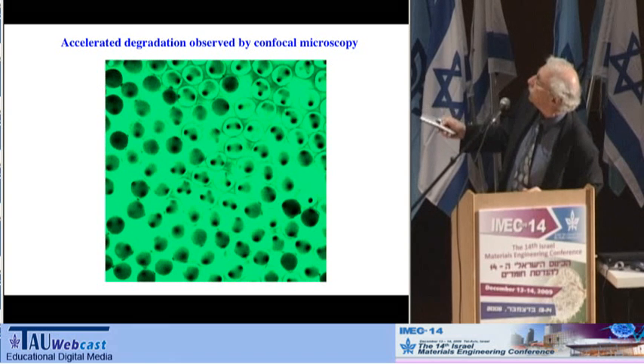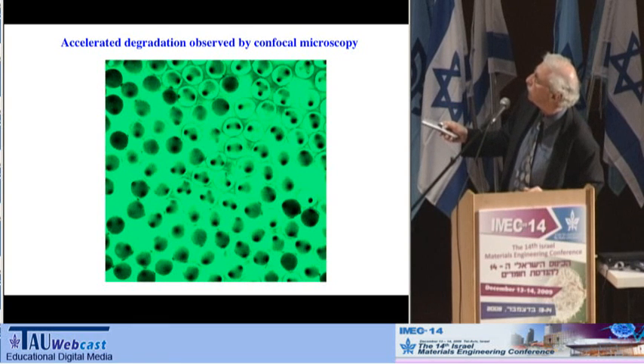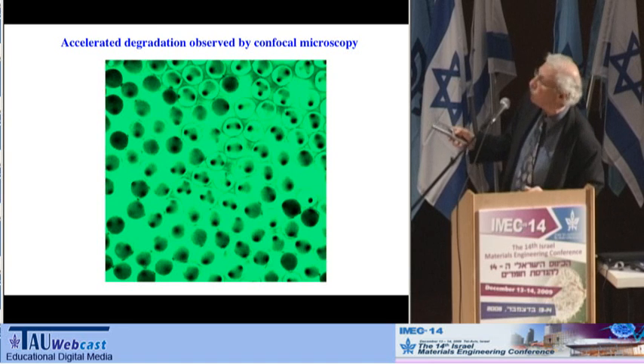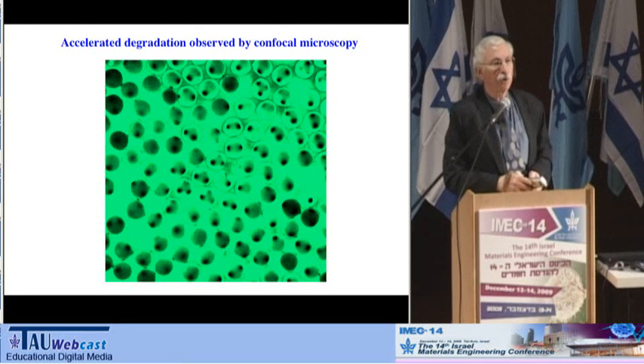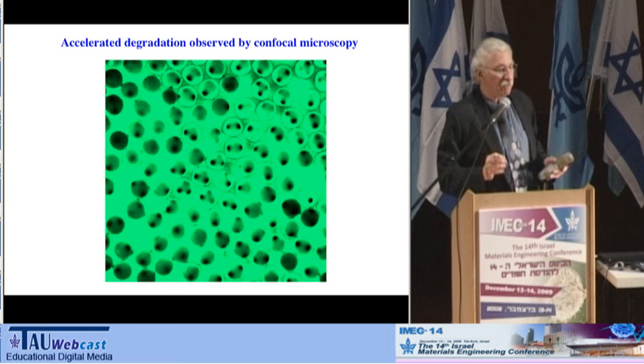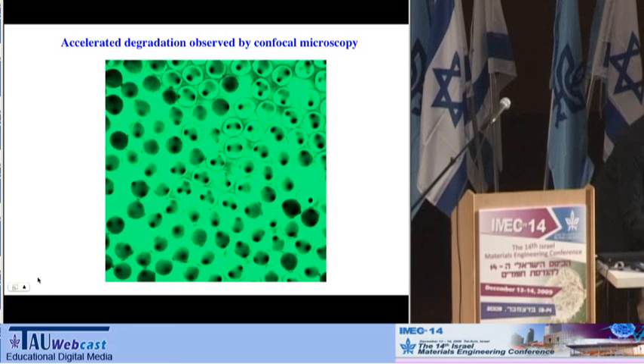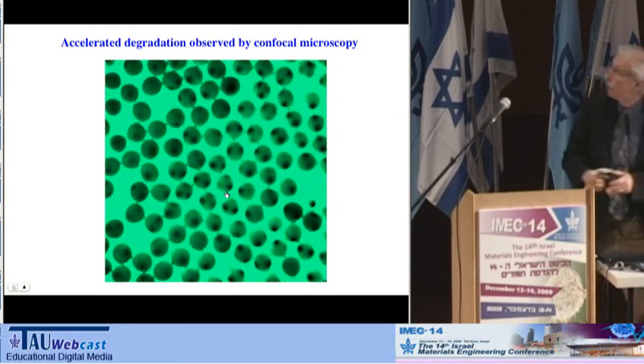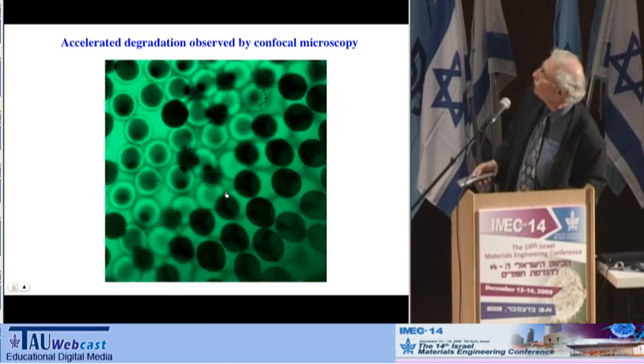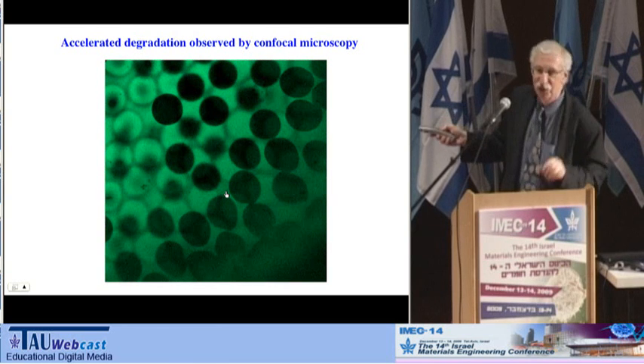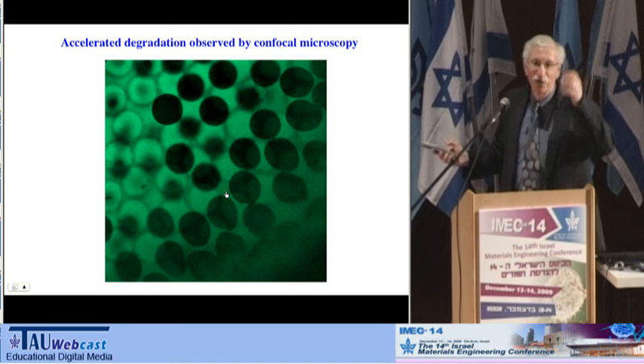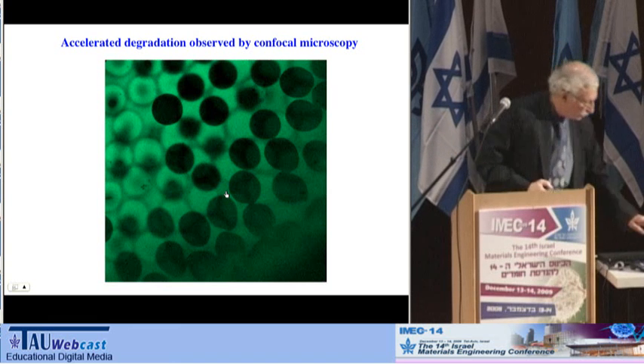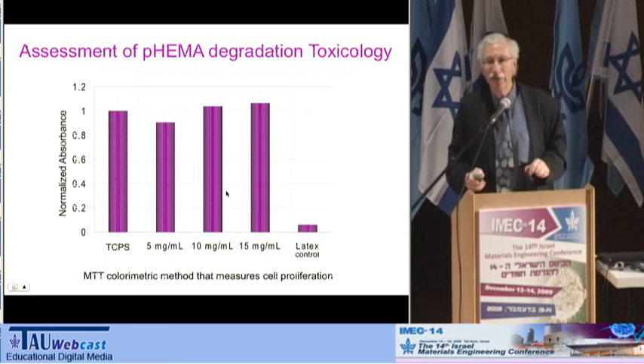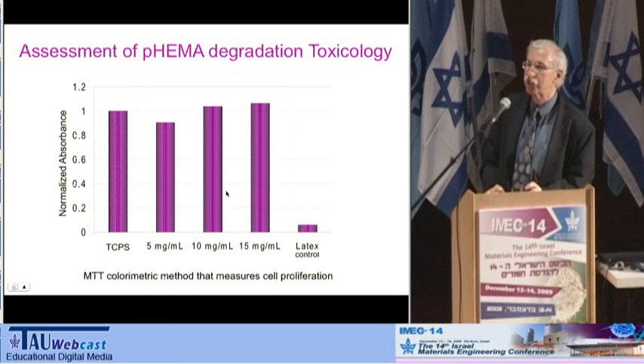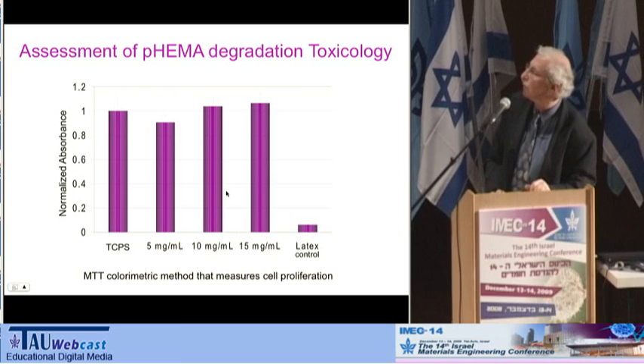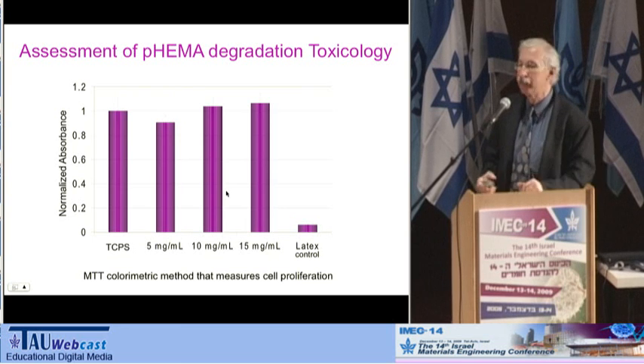And this is a section of this material on the stage of a confocal microscope. We're just going to add some strong KOH to rapidly degrade it. Let's see if the movie's going to work here. Yeah. So add the KOH, and although the movie didn't complete itself, the whole thing goes away. I'm not sure why it didn't do that. Anyway, the whole thing does completely dissolve off the stage of the microscope. We can watch the degradation process, this swelling and then dissolution.